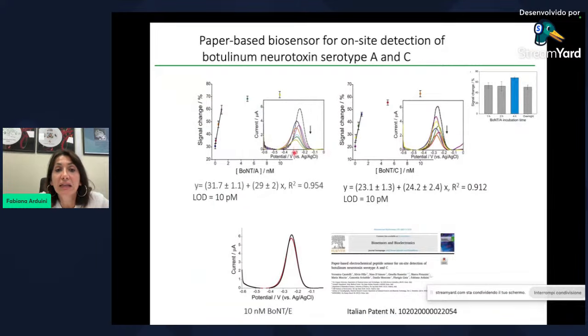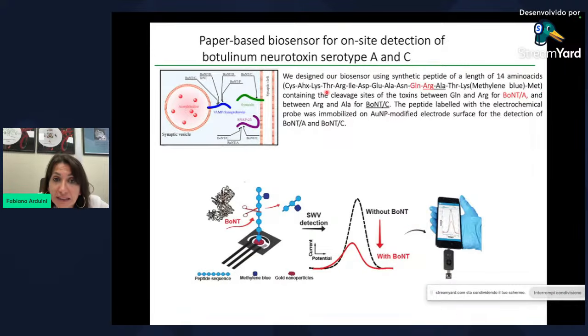And we demonstrated the high sensitivity of this device for botulinum toxin A and C. This is the calibration curve, we are able to detect both botulinum toxins at 10 picomolar. In addition, we demonstrated that it's possible to have selectivity when we tested, for example, botulinum toxin E, because there is no decrease of the peak. Why? Because, of course, this cleavage site is not present in the peptide that we synthesized.